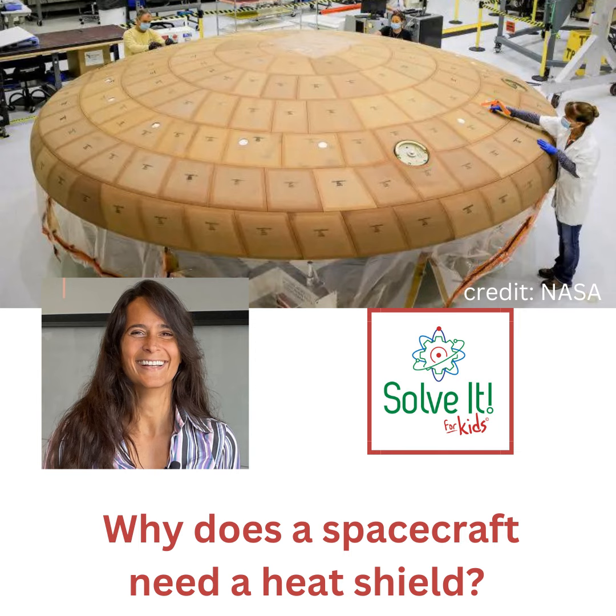I don't mean to get too complicated, but that adhesive has to withstand a certain amount of temperature. That way we don't have to make the heat shield so thick that we're using up a lot of mass, right? It becomes so heavy. So we're trading this: we'd like to make it as thin as possible, but we also need to not break the adhesive right through. This is where the material science comes in, right? Exactly. Yes. So that's one, right? We've got to be able to adhere these tiles correctly. I was telling you guys the configuration is different between Apollo and Orion.